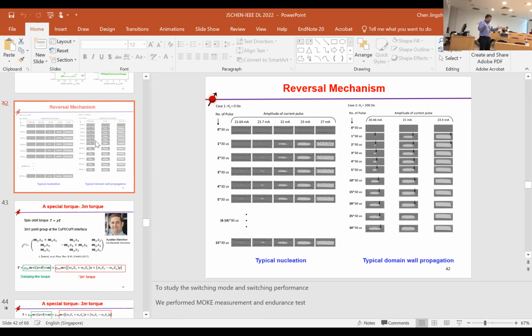In the past we say the spin-orbit coupling is from the atomic nuclei, right? But cobalt has a good perpendicular anisotropy, right? It's a light material. But where the large perpendicular anisotropy comes from is still the spin-orbit coupling. But that spin-orbit coupling is due to the spin coupling to the lattice. So the lattice itself also has spin-orbit coupling. We may also generate some new torque.